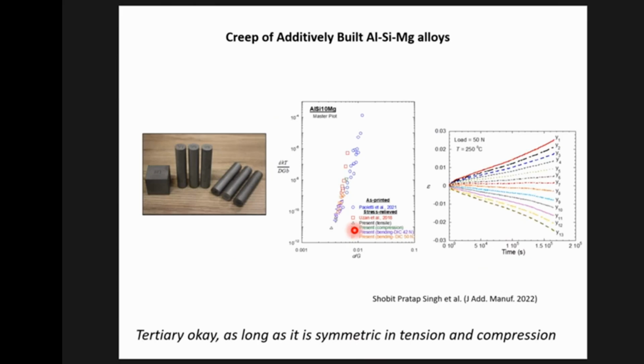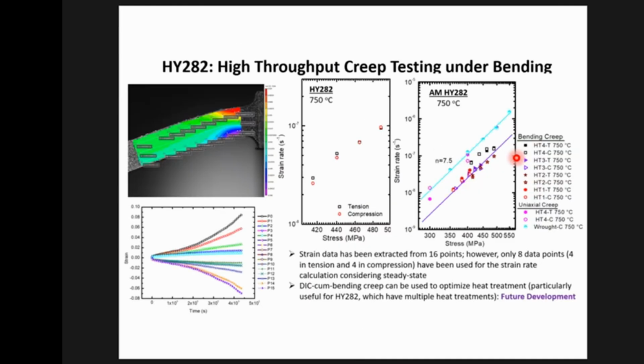So using this, one can do things like use additively made materials when materials are in short supply. I'll show you a bunch of curves like this. They basically tell you that the data you get from the literature and what you get from bending all fall on the same line. But essentially, you're getting multiple stress strain rate curves from one sample. And subsequently we got on to higher temperatures. This is a Haynes 282 alloy at 750 degrees.